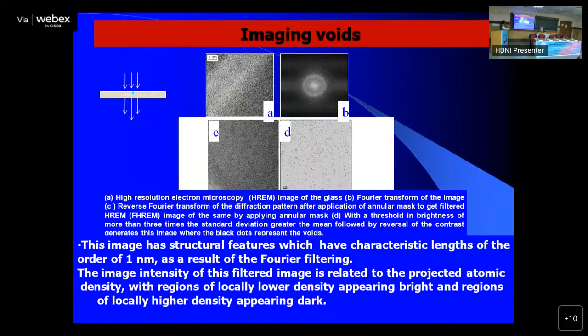Here, just quickly, I will tell you what happens if you have an open space or void here. The transmitted beam will get less absorbed, and therefore it will be intense as compared to the adjoining regions where this open space is not there. So absorption will be less here and absorption will be more in these regions, and therefore these regions will look dark and this region will look bright, and you have these white dots here which represent the voids inside the material.